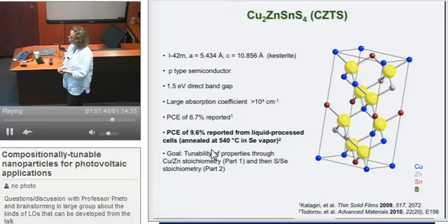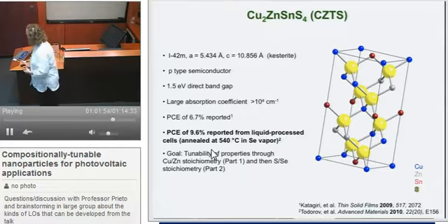So what we wanted to do was come up again with a solution synthesis route where we could control the amount of selenium in our particles and then study the physical properties as a function of composition to figure out why the selenium was so important.